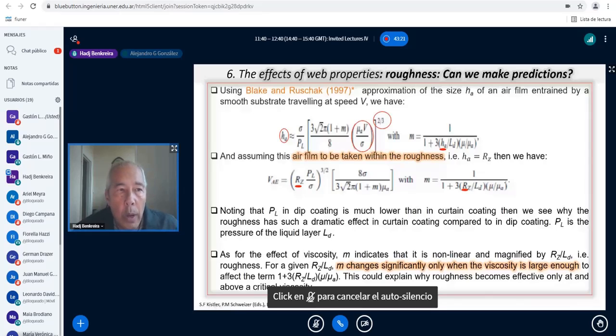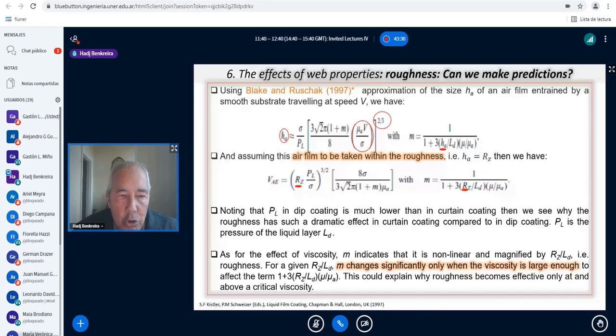Okay. Now, when we look at it theoretically, we can see that the air film that can be entrained is the same. It's proportional to the power 2/3 of the capillary number, whether you have a gas or whether you have a liquid. And when you combine this with the roughness, and if we assume that the air film is going to be housed in the roughness, then you can have a direct correlation between the air entrainment velocity and the roughness. And also you will see the nonlinearity of the viscosity of the liquid. And that explains why there is a critical value of the viscosity before the roughness becomes effective.